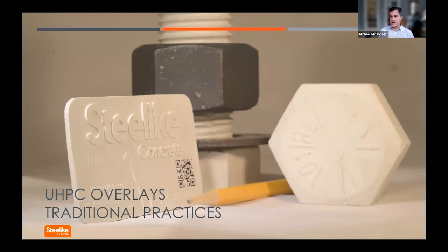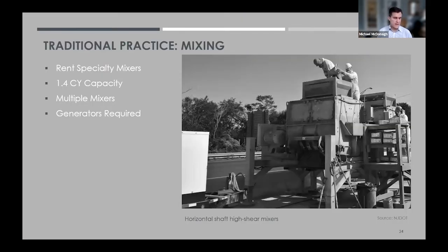Now for UHPC overlays, overlays have only been around in the US using UHPC for about five years. During that time, it's again pretty much the same practices. Similar to joint fills, the contractor must rent specialty mixers from the UHPC supplier. Because of the higher volumes involved, typically they use larger volume mixers, horizontal shaft, high shear mixers, which max out at around 1.4 cubic yards capacity. Again, typically multiple mixers, and the contractor must provide rather large generators. In fact, you can see one in the left foreground of this photo.